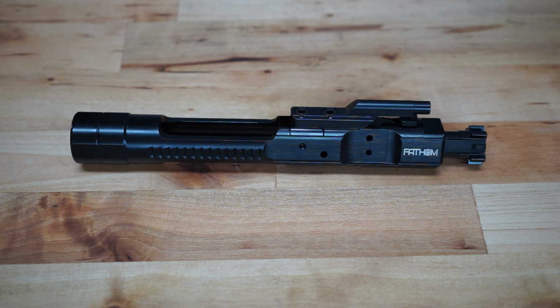The bolt itself is magnetic particle inspected, and the bolts are lot high pressure tested. They're not individually high pressure tested. This is due to the destructive nature of high pressure testing. So when we test one bolt, that bolt gets scrapped out of a lot, and basically we're not trying to induce any premature failures of this bolt. High pressure testing, people go back and forth on whether it's good or bad. I feel that it's pretty destructive in nature, and if we lot test and we're good to go, I feel like since we're using solid round stock to machine, we're using quality materials, that lot testing is good enough, and you're not losing up to 60% of the lifespan of the bolt by performing a high pressure test on every single one.